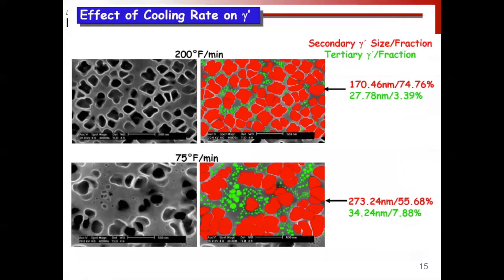So if we cool at a relatively fast cooling rate, 200 degrees Fahrenheit a minute, right? Again, Comic Sans, you can see I stole this slide from Jim Williams. We see we have a fairly high secondary gamma prime fraction of 75%. The secondary gamma primes themselves are fairly small, and we have a small amount, about 3 to 4%, of tertiary gamma prime in the structure. If we cool it slower, we have larger secondary gamma prime, a smaller fraction, and a larger amount of tertiary gamma prime that's going to form.